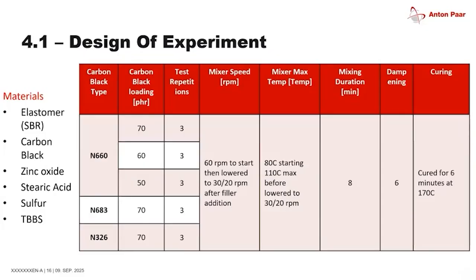So I picked 3 different carbon blacks. These are all standard reference carbon blacks. One is an N660, which is middle of the road in its structure. I will get into this a little bit later. Then we have an N326 and an N683. One is a very high structured carbon black, and the other is a lower structured carbon black. From the N660, we varied the loading, so we have 50, 60, 70 PHR. And from the other ones, we stayed with the high one. So we have one that we like a lot, where we have 3 different loadings, and we have 3 different materials that we tested at the high loading.